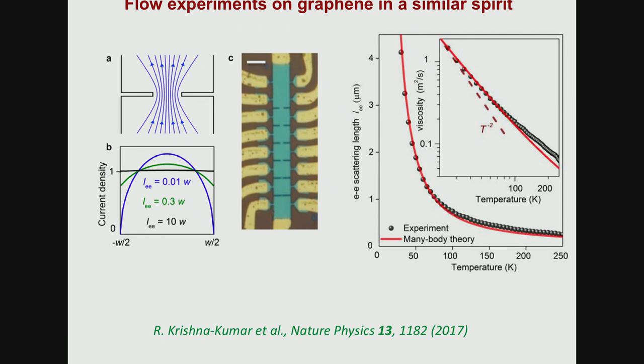And what they published is a paper, based on theory from Levitov, who tends to be right on these things, saying that you can do a ballistic calculation, and you would think that a purely ballistic, super pure material with no viscous effects would be the most efficient way to get current to flow through those constrictions. But he pointed out that because of this viscous channeling, it isn't. The viscous fluid beats the ballistic limit. So you end up getting higher conductance through those restrictions because of the hydrodynamic effects than you would have had in the best sample you could have thought of. And that potentially has technological ramifications as well as pure physics ones.